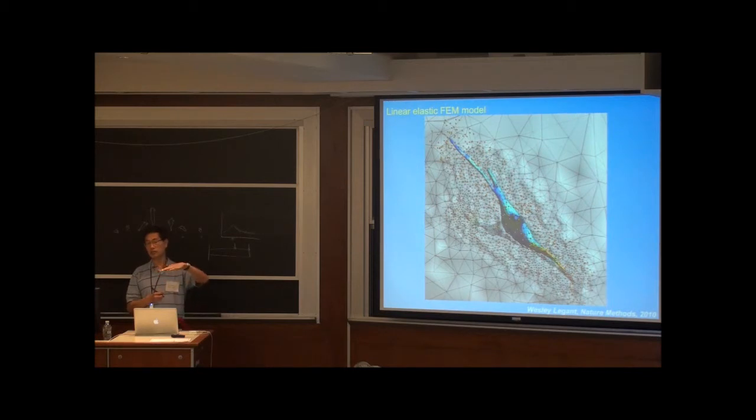For the 2D situation, it's always a half space. So you just have to do it once. But here, for every time you get an image, you have to then redraw what the cell looks like and regenerate a new finite element model of that gel. Once you have it, then if you have the deformations of all the beads and where they are, then you can generate the strain maps, right?